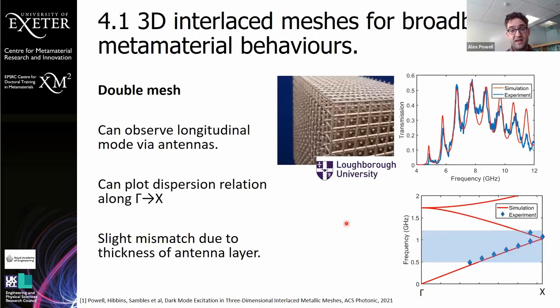We had these fabricated, again, using SLS by some collaborators at Loughborough University who do a lot of great 3D printing. We dip coated this in some conductive copper paint and observed the transmission again. And we can see that the simulation and experiment, when you take into account the surface roughness and the conductivity of the paint, match up really well. And we're able to use these Fabry-Perot resonances again to obtain an experimental evaluation of a limited section of the band structure. And again, we get really good agreement between experiment and theory.